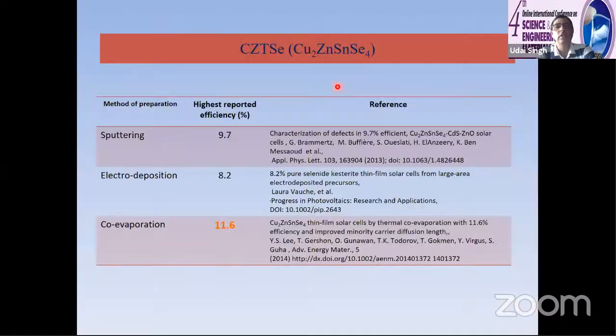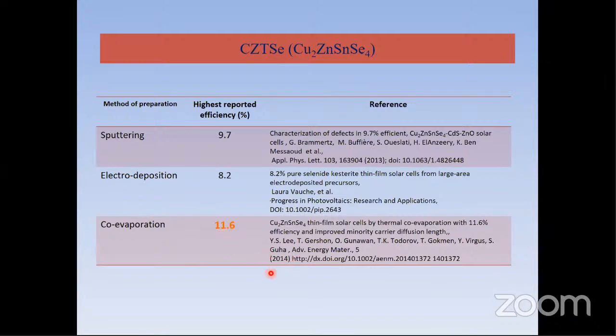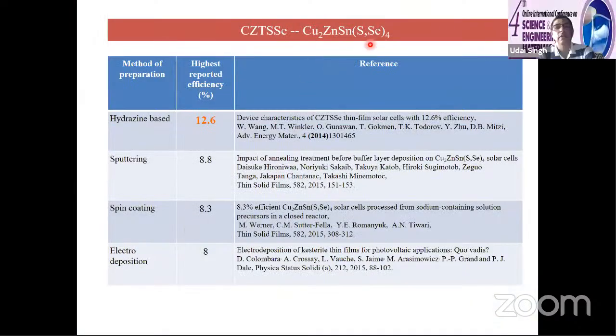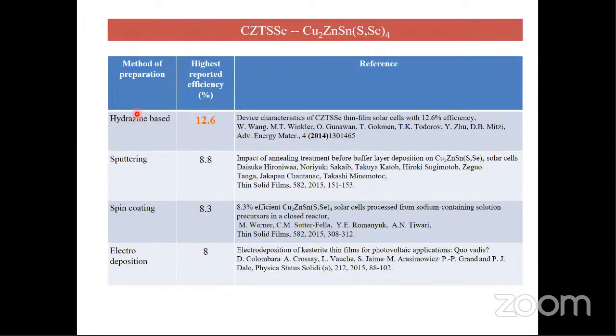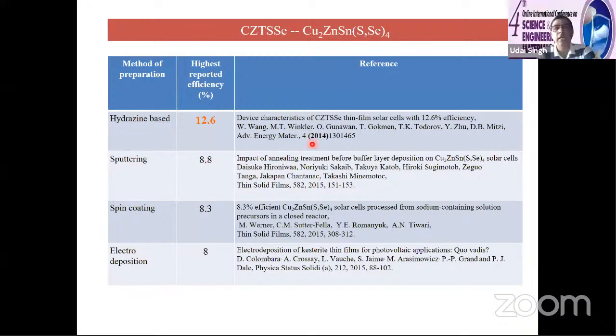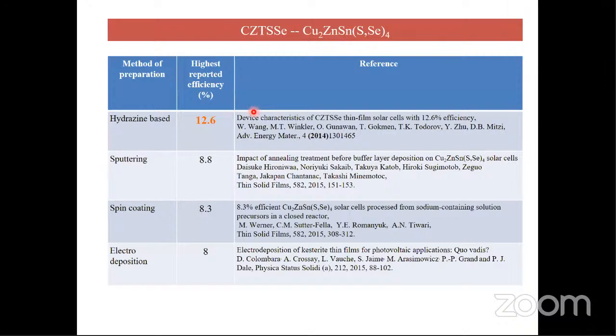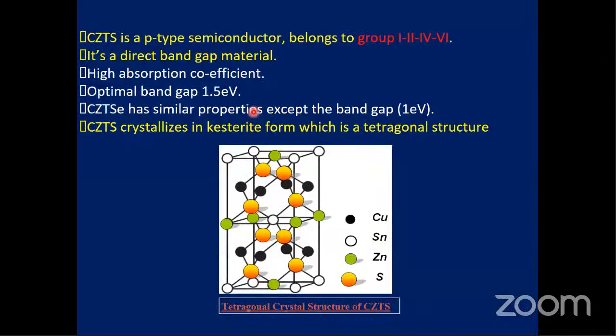Similarly, if you go for the copper zinc tin selenide, using co-evaporation it has given 11.6%. That is again 2014. Again 7 years, no increase in efficiency. And similarly for sulfoselenide, the highest efficiency is around 12.6, which is a hydrazine-based material. And then sputtering people have done. So it's again 2014. So again 7 years, no increase in efficiency is observed.